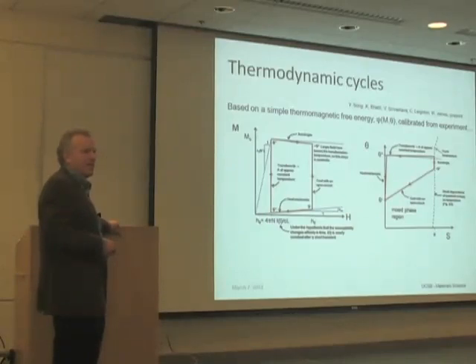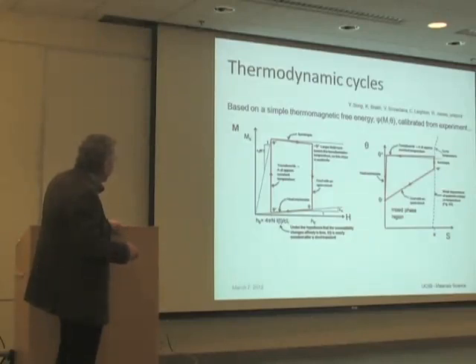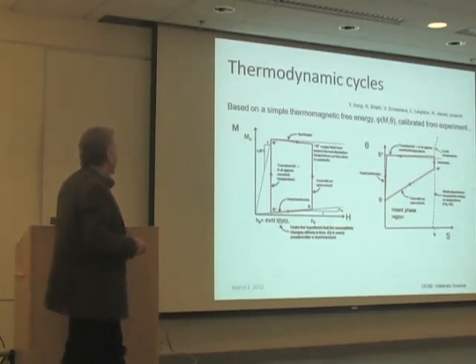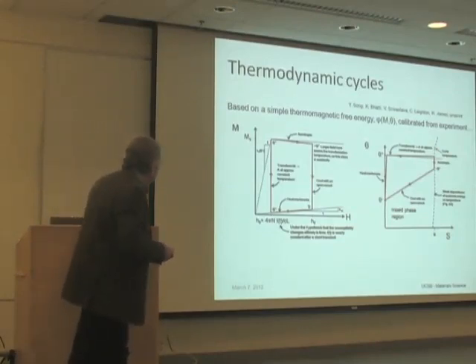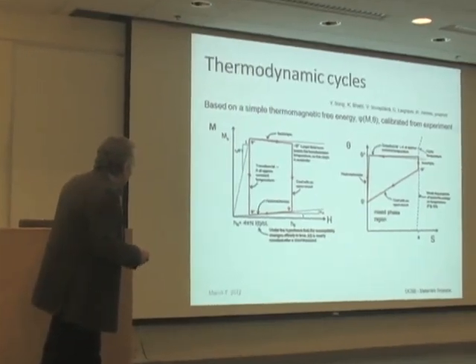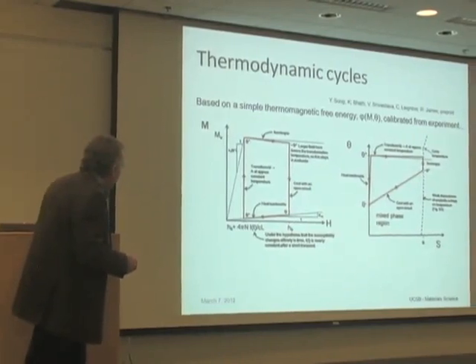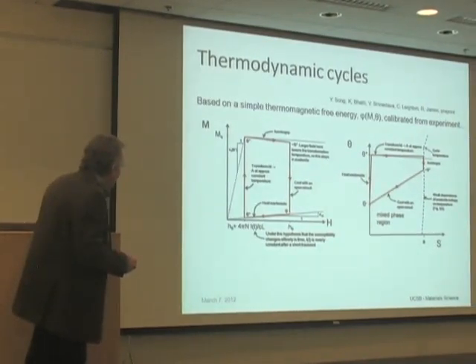It's interesting to look at the thermodynamic cycles. They're represented here. We actually built a little free energy. We calculated the entropy from this, and we have a nice representation of the entropy of this material, including these phase transformation and magnetism. But the main thing here is what happens during the thermodynamic cycle with the applied field: when it starts transforming, it starts inducing a current in the coil.